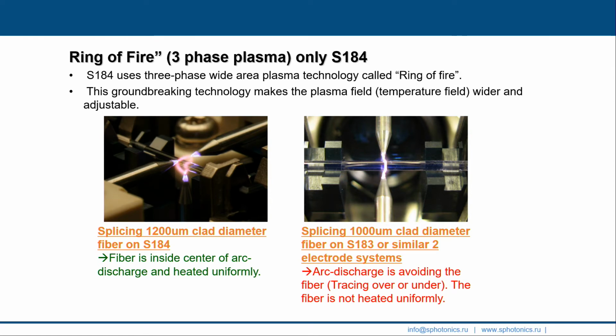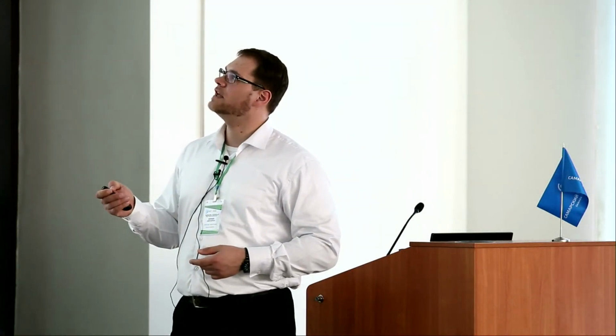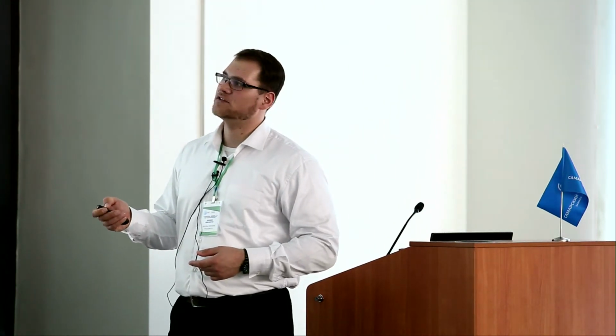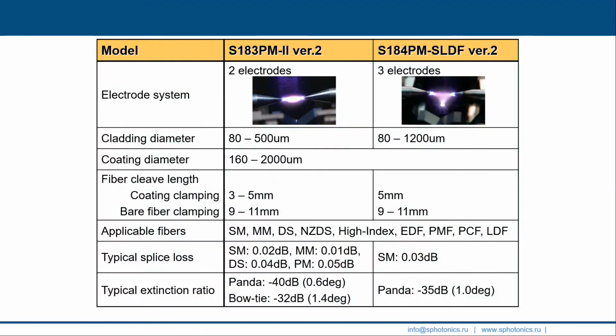You see here, the operator tried to splice a fiber of big diameter with the conventional two-electrode method. We see that the plasma current goes from one of the lateral sides of the fiber, but it doesn't affect the whole lateral side, the whole splice. Here is the specification. We just need to know that the S183 splices fibers with diameters from 80 up to 500 microns, and the 184 is used to splice from 80 up to 1200 microns.